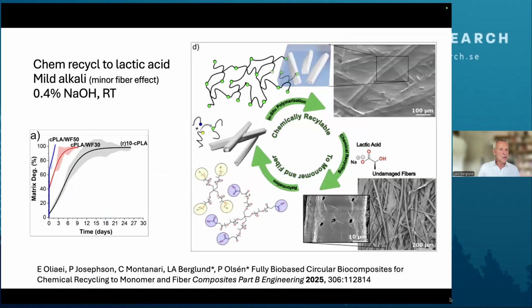It's very easy to recycle this, and we are able to do this at low sodium hydroxide concentration, 0.4%, at room temperature. And the remarkable achievement compared with what is in the literature is that it's possible not only to reclaim the lactic acid, which is a monomer that can be reused, but also the fibers.